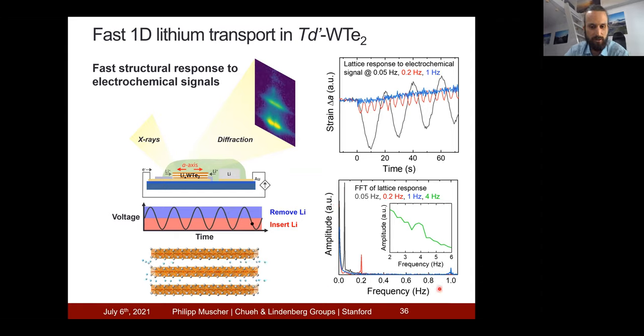which you can see more easily in the frequency domain. For example, for electrochemical signals of 1 hertz, we see this peak in the Fourier transform at 1 hertz. And we also see a peak even for excitations of 4 hertz. So with this, we see that close to the edge, we can drive the system on very fast timescales.